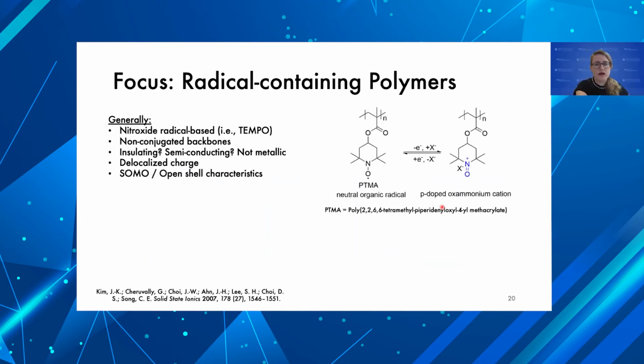Our focus here is going to be a radical-containing polymer called PTMA. This is the polymer that I feel is getting a lot of interest because it satisfies many of the challenges that we've been talking about. But it's part of a broader class of polymer that includes stable nitroxide radicals. So this polymer stores energy by the reversible oxidation and reduction of this nitroxide radical group, where I can oxidize it and take an electron away, and an anion will come in to balance the charge, and we'll call that doping. And the anion can be really any sort of anion from the electrolyte.